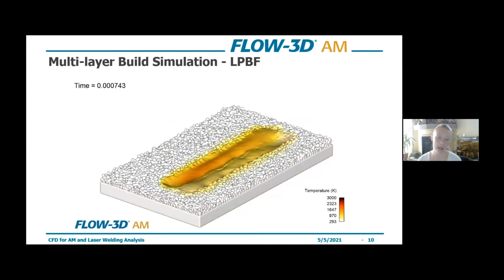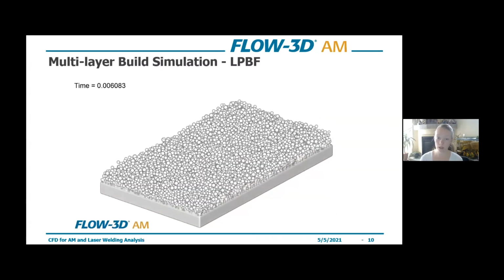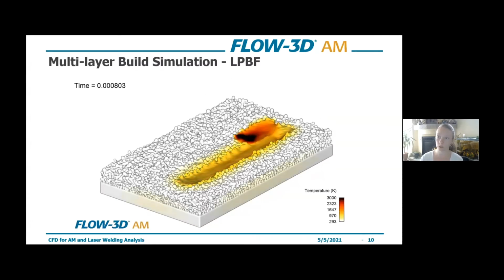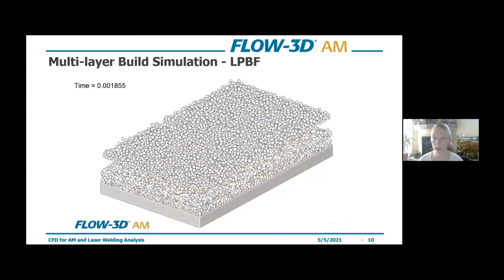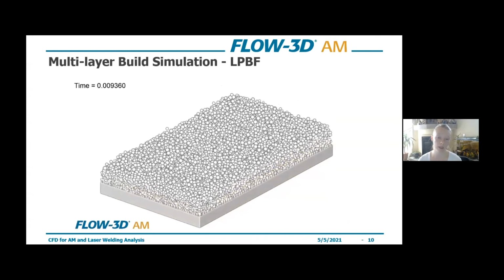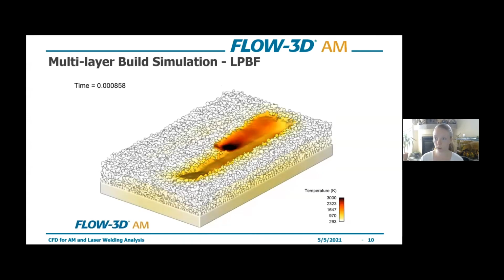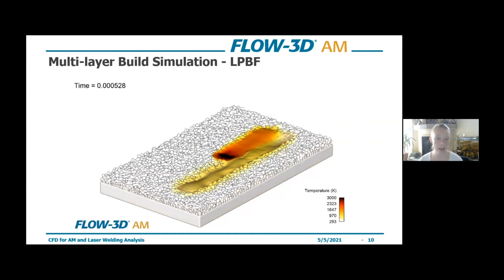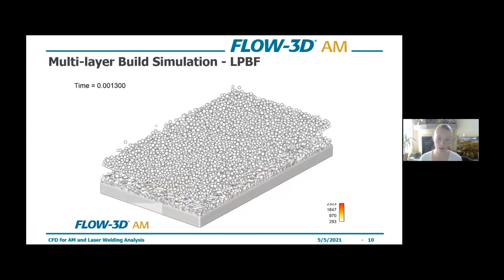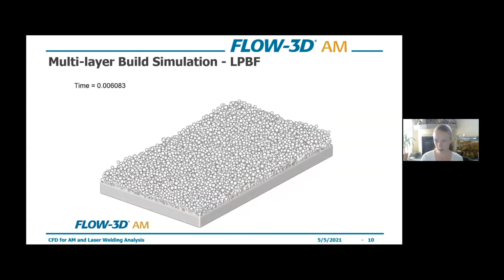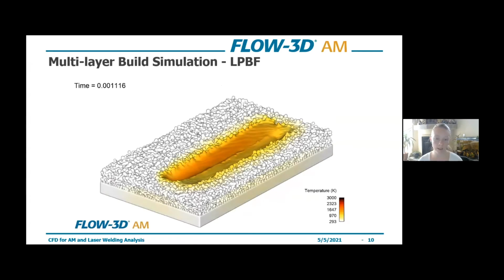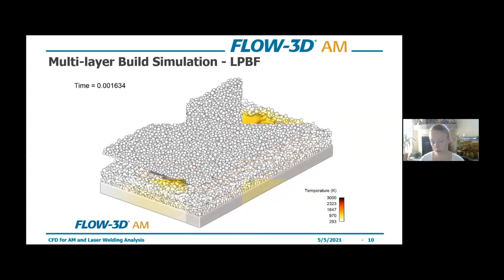kind of domain size. And we preserve the thermal history from each previous layer, so that in the subsequent layer, we're seeing the effect of remelting, any sort of void formation or mitigation. There's a lot of phenomena that happen as you build layer over layer, as you would, I assume, guess. And that is all something we can capture in these melt pool simulations within a few layers. And then you can take it over to your FEA tool and ignore the fluid flow and do the part scale build.